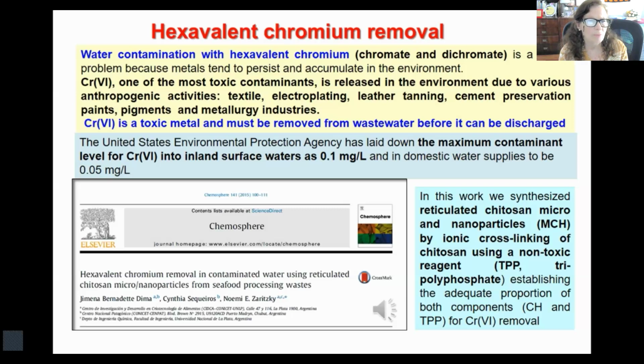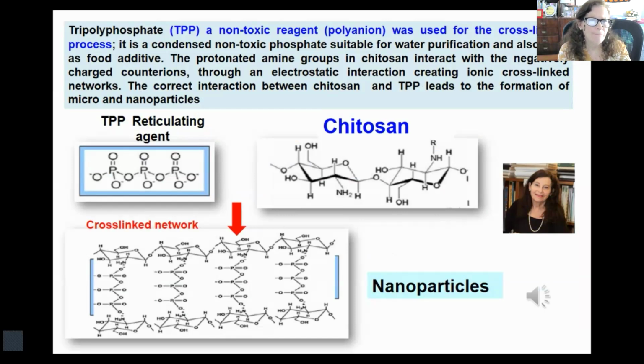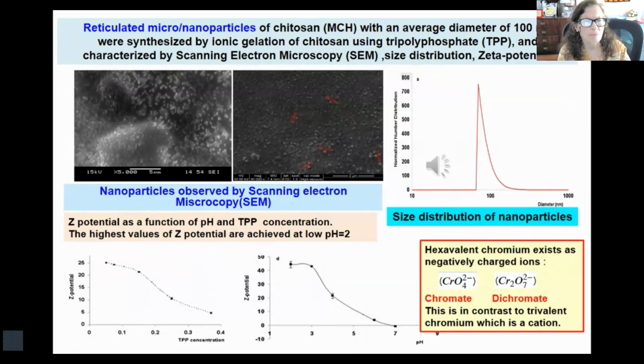In this work, we synthesized reticulated chitosan micro and nanoparticles by ionic cross-linking of chitosan using a non-toxic reagent, tripolyphosphate. Tripolyphosphate is a polyanion that interacts with the protonated amino groups of chitosan, forming the cross-linked network that is shown in the figure, and generating micro and nanoparticles in adequate concentration. Cross-linked micro and nanoparticles of chitosan with an average diameter of 100 nanometers were synthesized by ionic gelation of chitosan with tripolyphosphate and characterized by scanning electron microscopy, size distribution, and zeta potential.